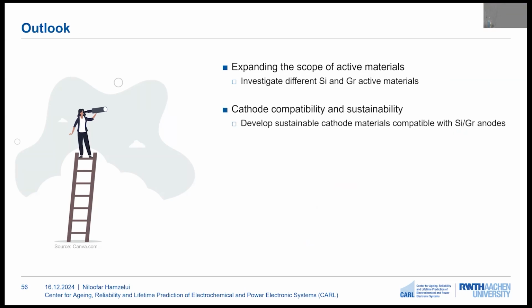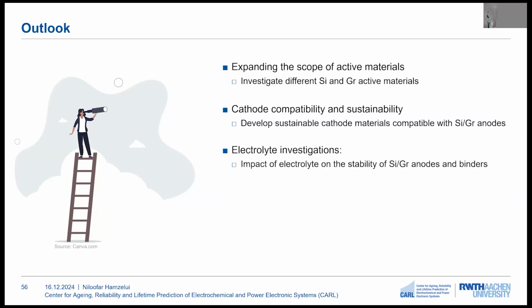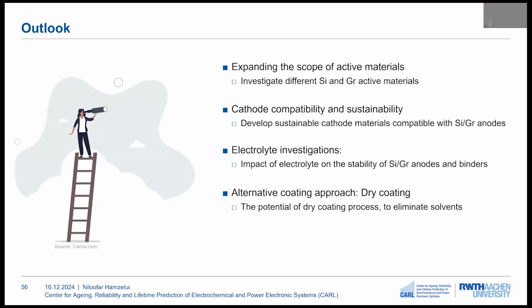Also, it should be noted that the lithium in lithium-ion batteries comes from the cathode side. So the cathode also needs to be further investigated to use more sustainable chemistry, which is adaptable to be used with the silicon-graphite electrode. The electrolyte is also of high importance, especially in the case of increasing the amount of silicon. And the impact of electrolytes, such as electrolyte additives or electrolyte salts, can also be investigated on the electrodes and the binders.